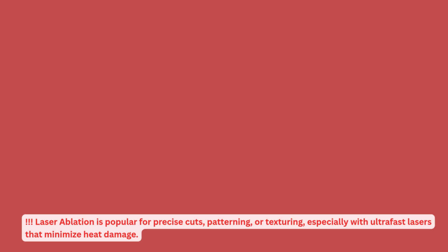Laser ablation uses pulsed light energy to precisely vaporize materials like polymers, ceramics, metals, and glass. It achieves resolutions from around 100 nanometers to a few micrometers and is maskless, with minimal heat when using ultrafast lasers. In ultrafast laser ablation, ultrafast refers to extremely short laser pulses, often in the femtosecond range. These pulses deliver high energy in brief bursts, vaporizing material precisely while minimizing heat damage. Although scanning speed affects how fast surfaces are processed, ultrafast here mainly describes the pulse duration, not the scanning speed.